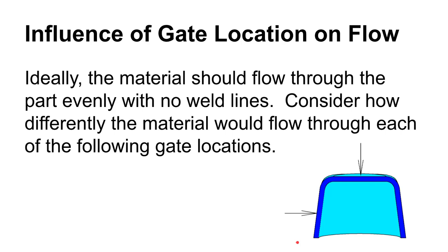Where you gate can make a difference in how material fills the mold. Take a plastic part like a cap or bucket: if you fill right from the center, the plastic flows out in all directions equally with no weld lines or knit lines. However, if you gate from the side, the plastic has to go all the way around and you'll probably wind up with a knit line going down the opposite side. Gate location can influence both the cosmetic appearance and the strength of the molded part.